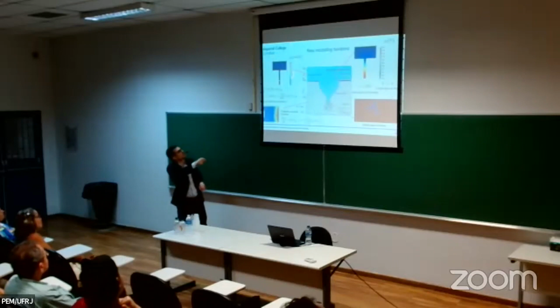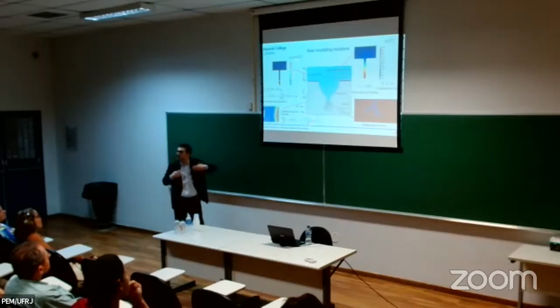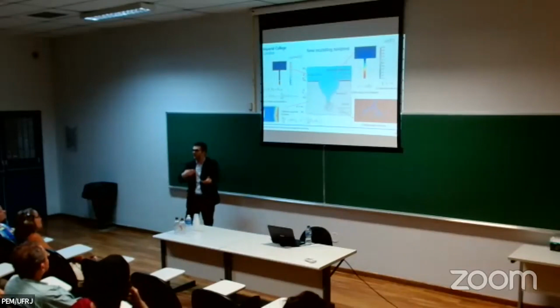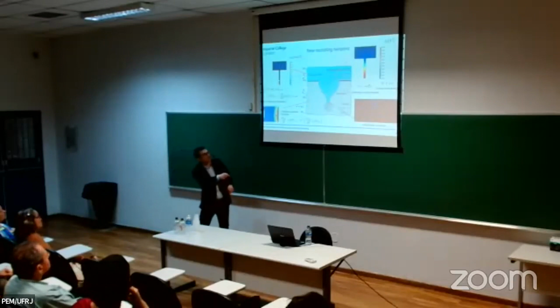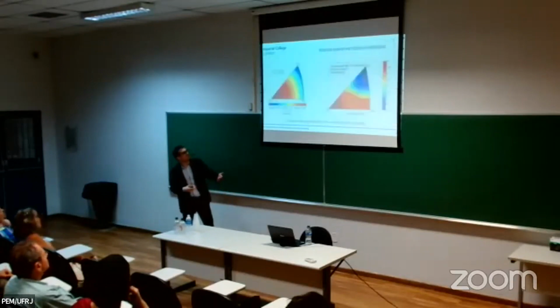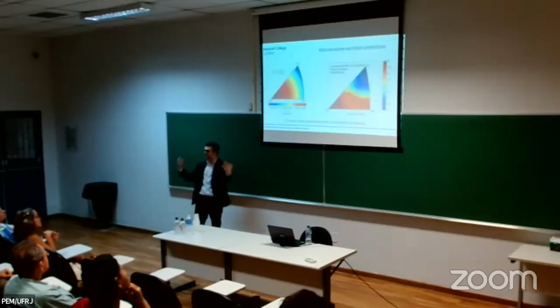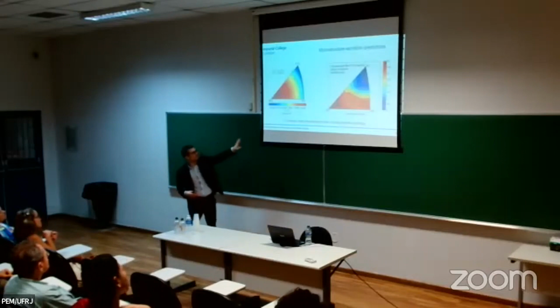So we can capture the role of the electrochemistry, we can couple that with those hydrogen problems before. Occasionally we have hydrogen uptake into the metal as a result of the corrosion process. We can capture also intergranular corrosion here. You can see here the role of the microstructure. We know that the microstructure plays a role from a mechanical point of view. You have this mechanical anisotropy, but also we know that corrosion can be anisotropic. So corrosion rates are sensitive to the crystallographic anisotropy.